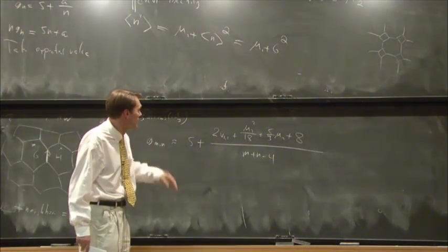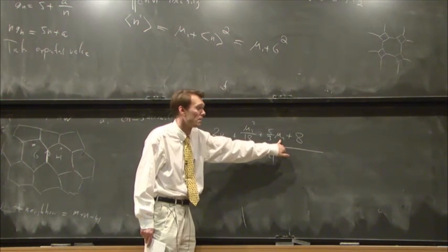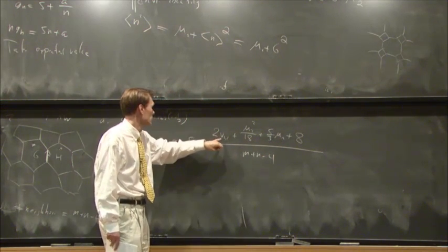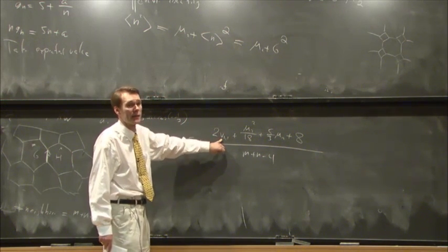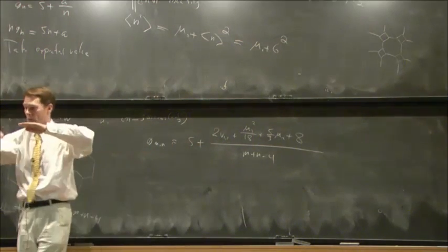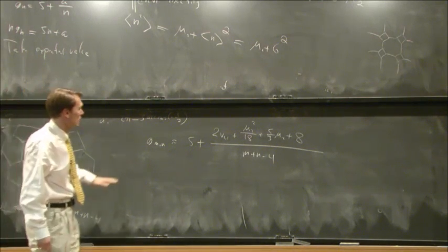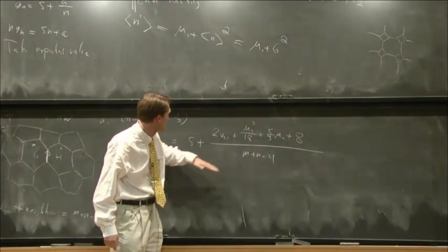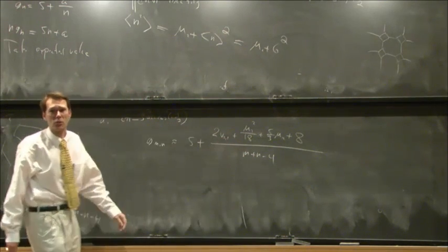So I have to tell you what it is. Mu2 is still the variance, and mu11 here is a covariance between two neighboring grains on their sides. So yet again, you notice that you have this nice hyperbolic relationship. But it's not as good, because when you look at Weaire's suggestion here, the nice thing is that the covariance between two neighboring grains doesn't show up.